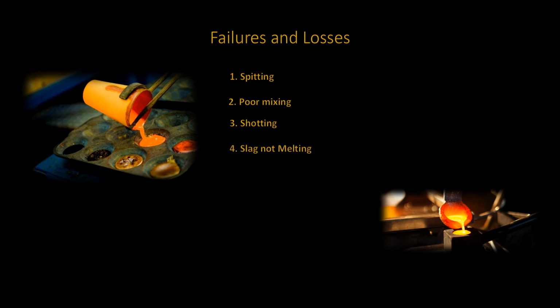If you find that your slag is not fully melting and is not fluid-like, add a little more borax, or the temperature may be too low for fusion. Scoria is something that is not wanted. It is usually caused by a large quantity of base metal oxides. It is best to add extra silica. If the temperature is too high, any copper will not be removed completely, and a second scorification will need to be done. The result will be a brittle button that will not satisfactorily cupel later.